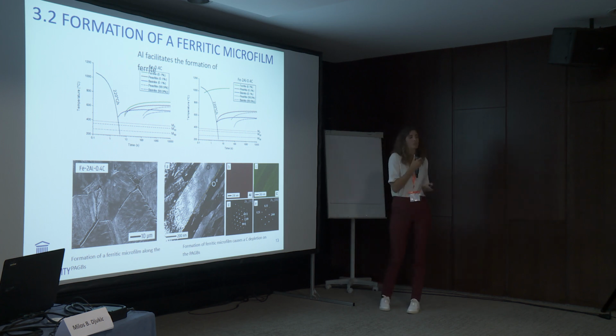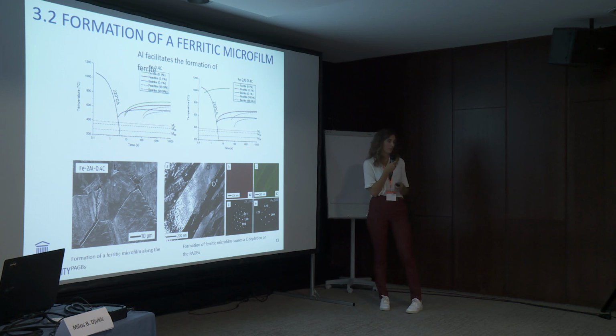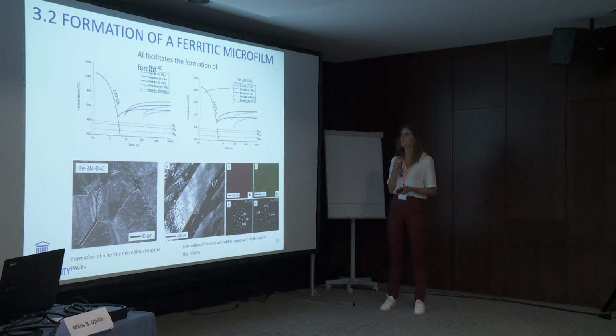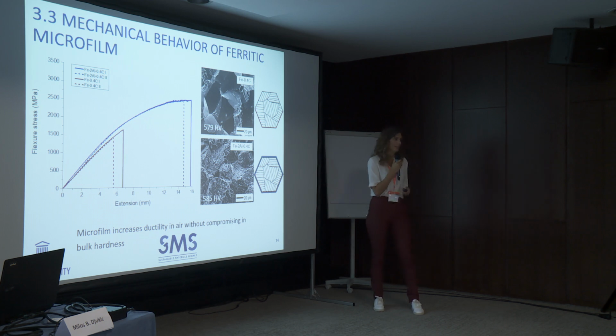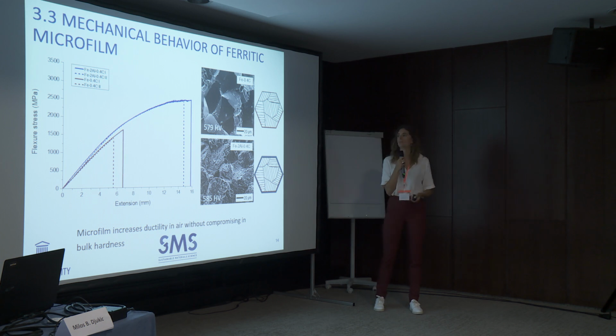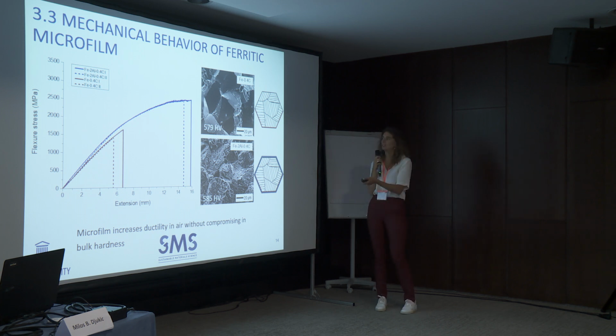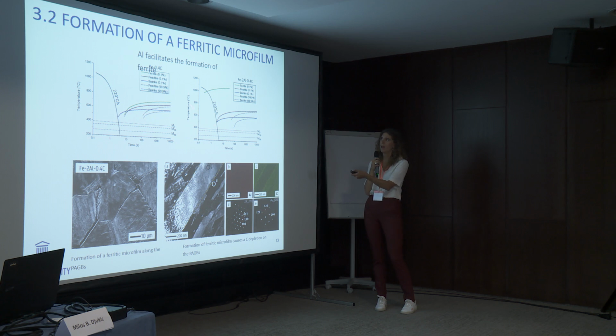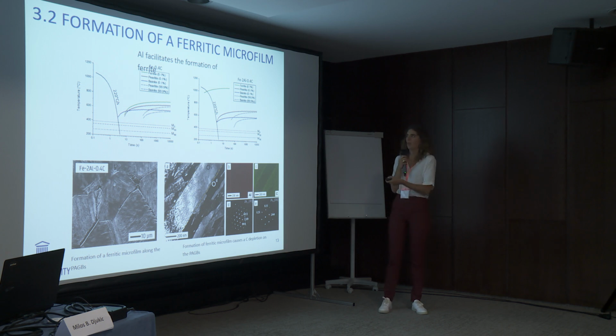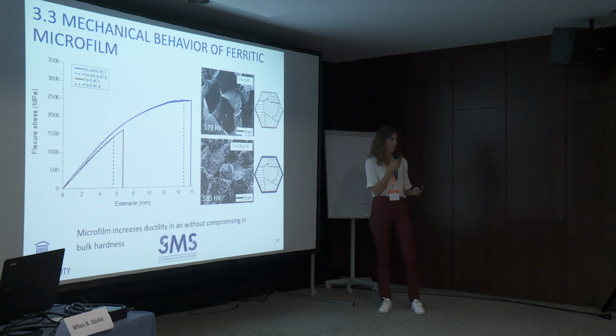Now, the most interesting part is, of course, to see what the effect of this ferritic microfilm is on the mechanical behavior. So I first did bending tests in air. The red curves correspond with the iron carbon steel without aluminium, and we really see a limited amount of ductility. This is a bit different than the things I showed before, but this is because both alloys were quenched from the same high austenitization temperature to really avoid the effect of the austenitization temperature. Same results were obtained just by comparing the iron 0.4 carbon steel as I showed before, but since time is limited, I only showed this result.